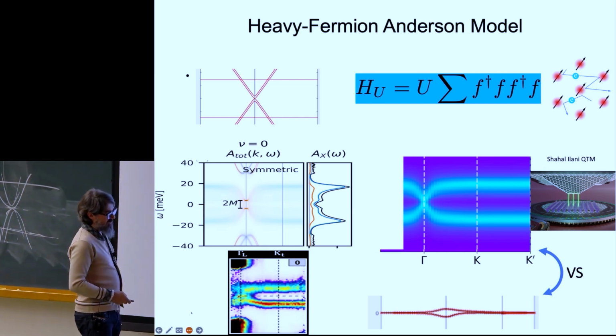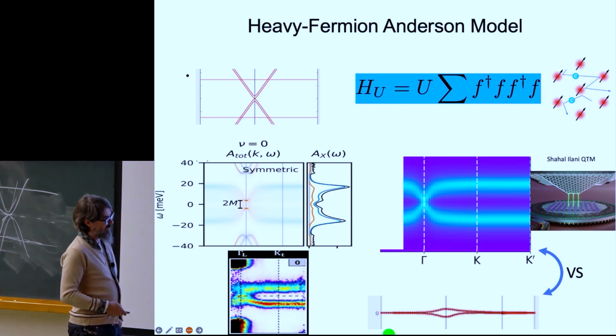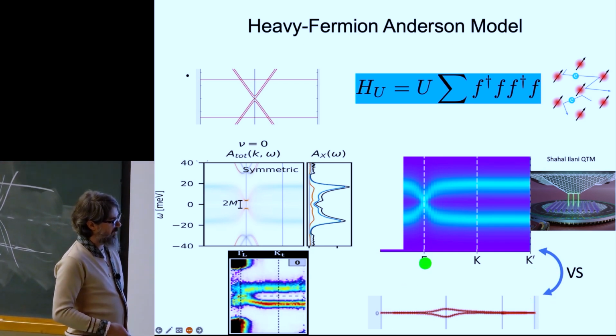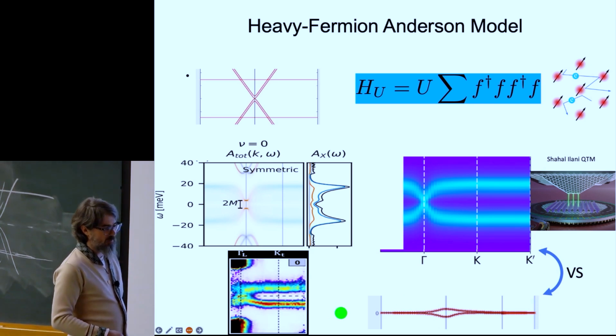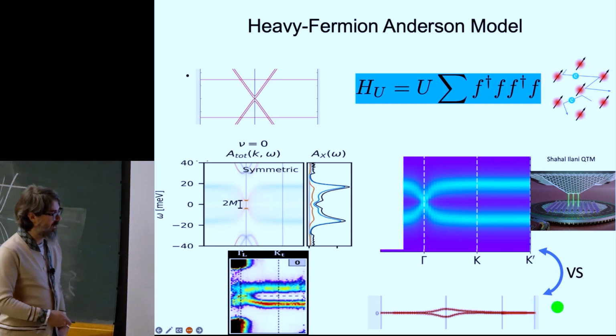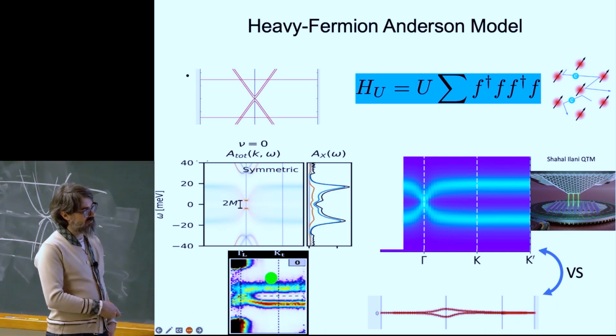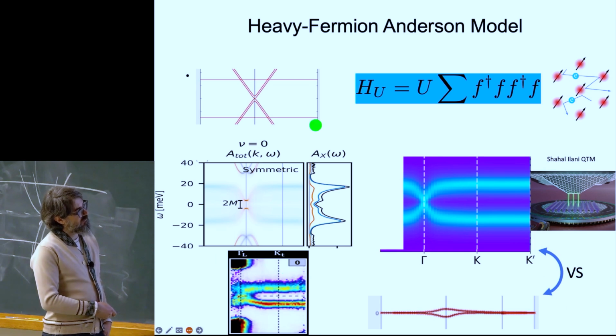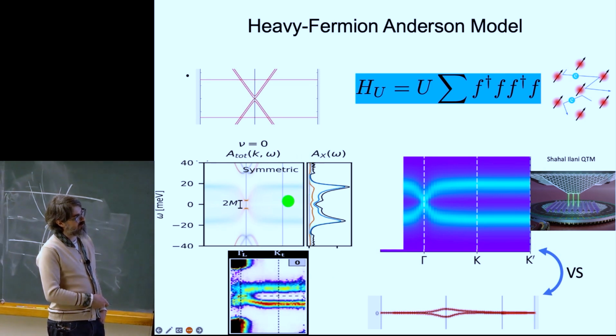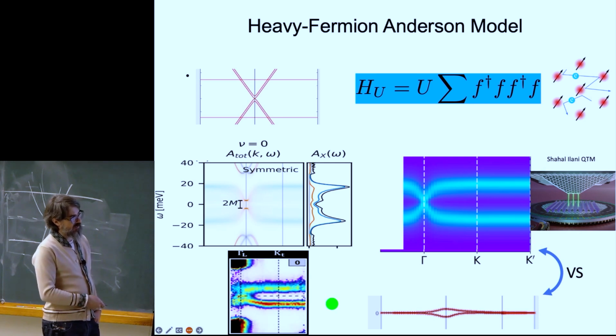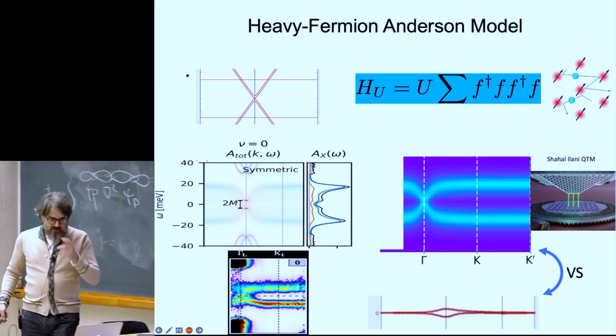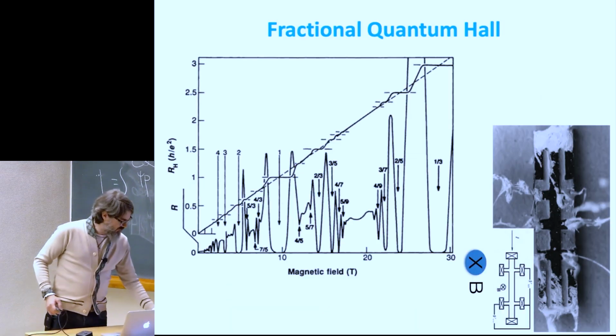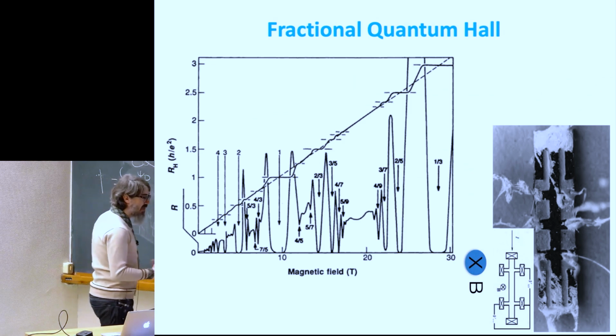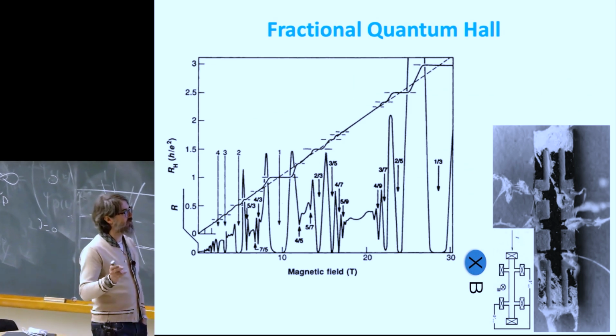And what I can tell you, so the paper is not published, but you can see the talk at the Flatiron for his data. At large angle, the spectral function looks non-interacting, but at low angle, i.e. at the magic angle, it looks like this. This is the K point, this is the L point. And you can see how even the energy scales match, or you can't see because I haven't showed them here, but this energy scale is roughly some renormalized U of the order of 40, 35 millielectron volts. This is exactly right on the money. So this looks exactly like this function. So now, hopefully, I can convince you that these are simulators of heavy-fermion systems, which you can go through the Mott transition.